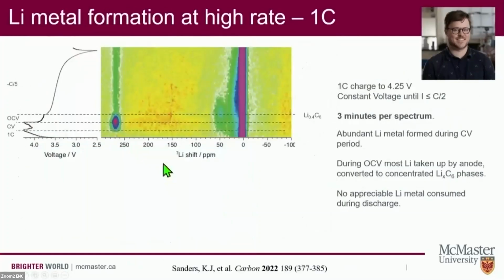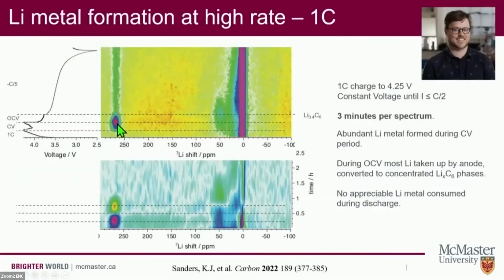And most importantly, we can cycle this cell at a high C rate and observe this plating of lithium within the cell. So the plating of lithium is so diagnostic in NMR because it's got this fingerprint way up at 256 ppm, separate from everything else. And so as we change the cycling conditions, we can force lithium plating in the cell. And then we can observe whether when we switch the potential of the cell, does that disappear or not? And some of it disappears and some of it actually remains constant. So the combination of the original spectroscopy plus the derivative spectroscopy give us a full picture of the lithium plating in this process.